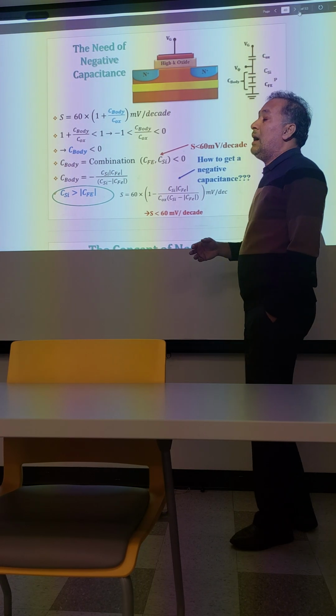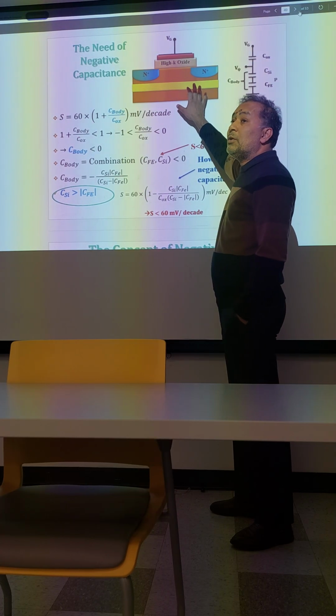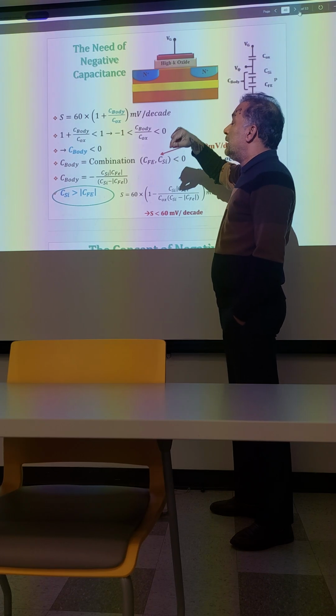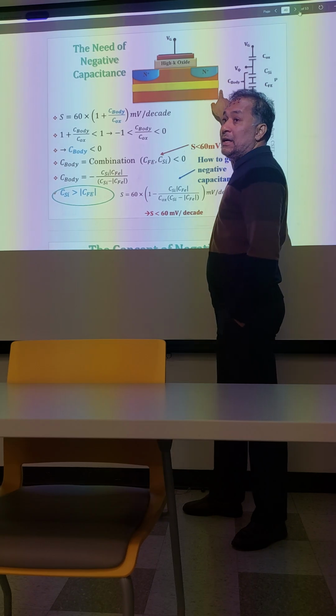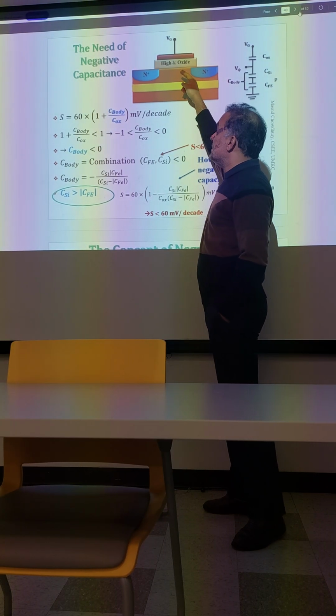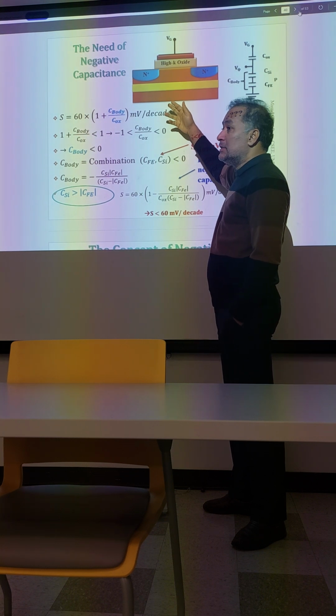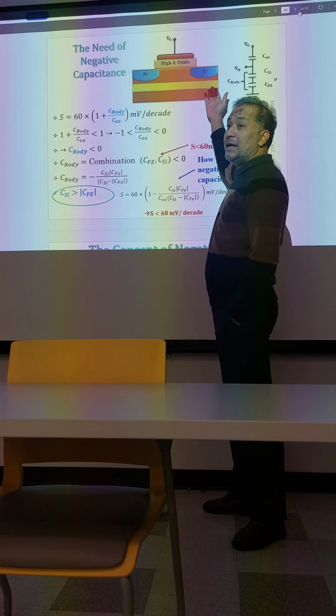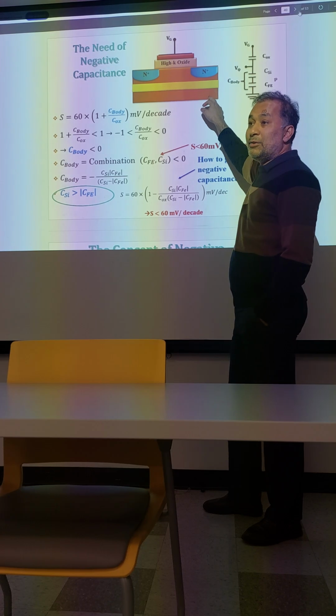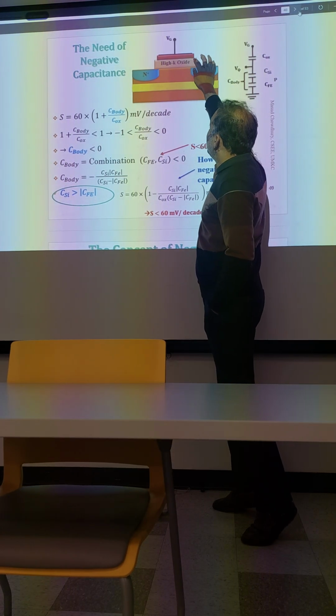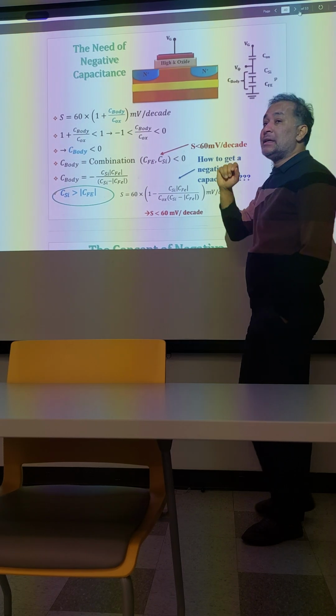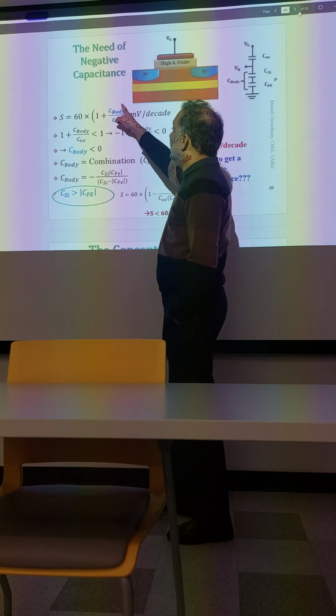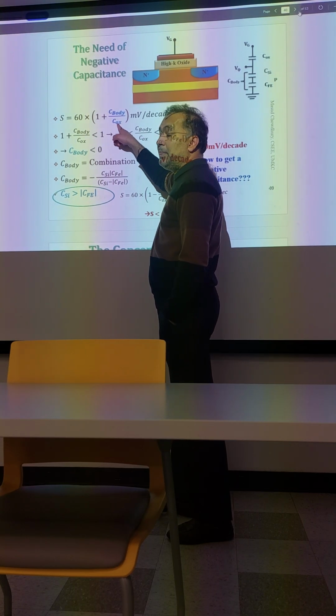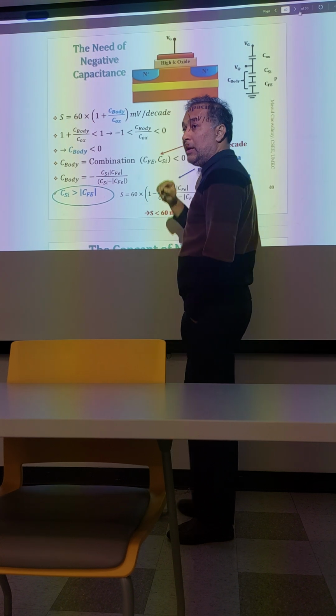So we started exploring, well, the possibility is, how about we use an SOI device structure. Inside the SOI device structure, there is a buried layer of silicon dioxide as an insulator to separate the active region of the transistor from the rest of the body. Very simple concept. How about we do not use silicon dioxide here, and use a ferroelectric insulator as the buried oxide, so that the negative capacitance will not be formed here, it will be formed here, because a ferroelectric insulator can provide negative capacitance under certain operating conditions. So in the fraction, if this one is negative, overall any one of them negative makes the whole fraction negative, and it will be smaller than 1.